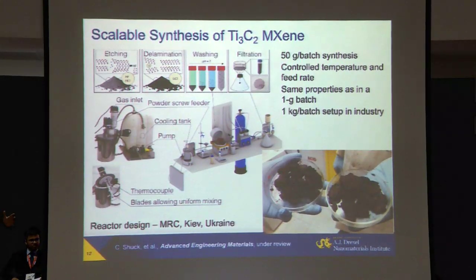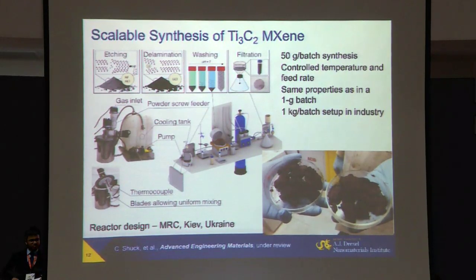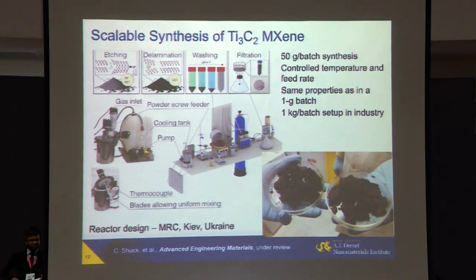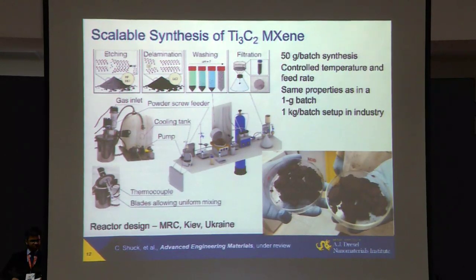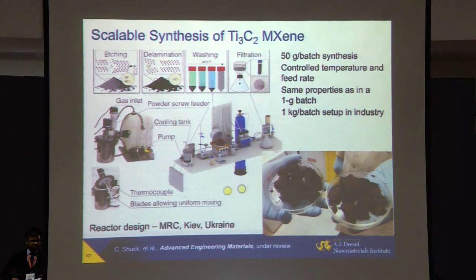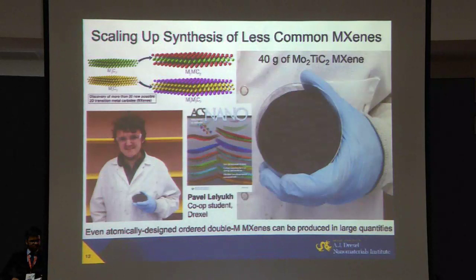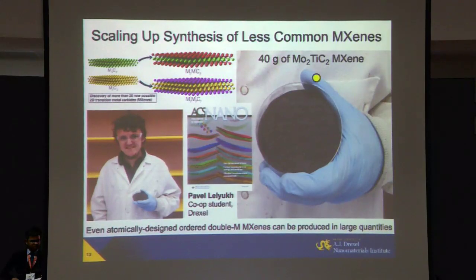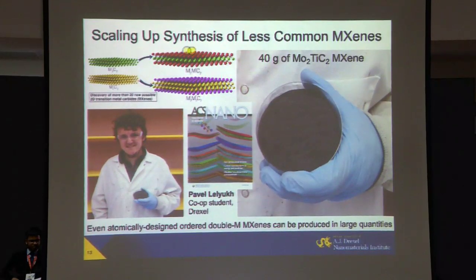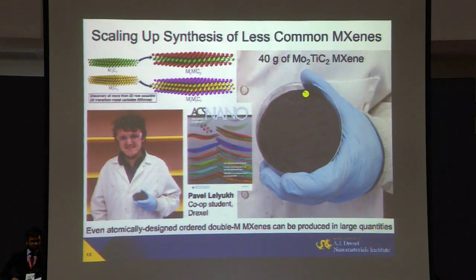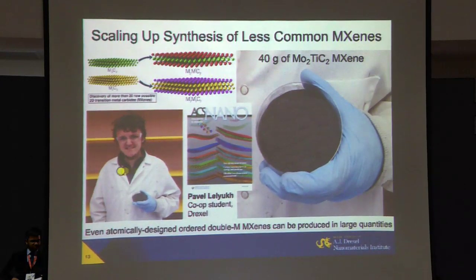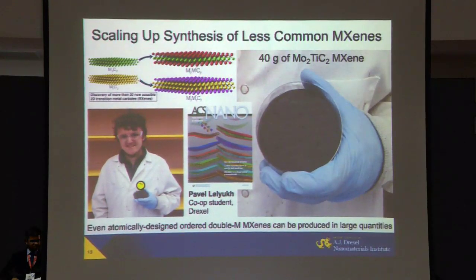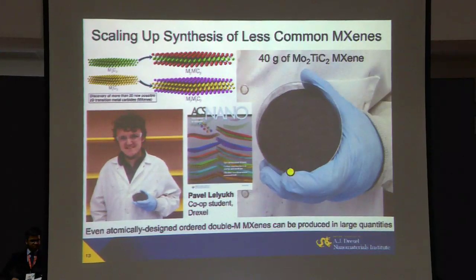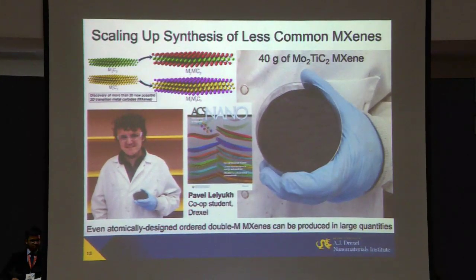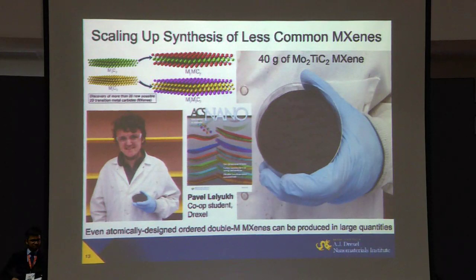You make it in a monolayer. You can cover a stadium surface with material made from a single batch in the lab. Moreover, not only simple MXene, this is titanium carbide Ti3C2, the most common one, but these atomic sandwiches, like Mo2TiC2, with moly on the surface, titanium in the middle, can be produced as well, and this is an undergraduate student, Pavel Lelyukh, holding about 40 gram in a petri dish of this material.